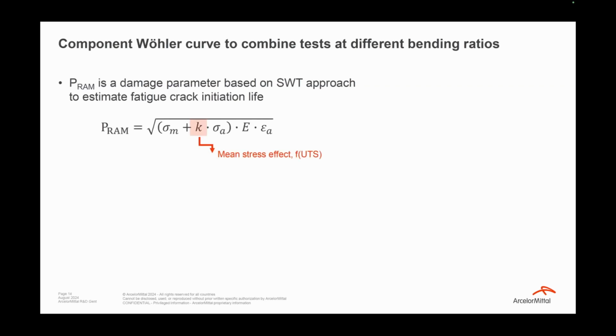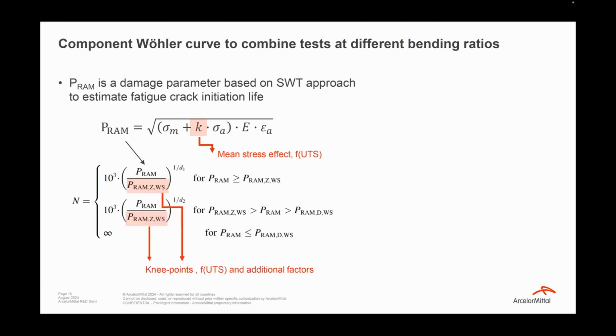There is a certain damage parameter which is called PRAM. This is based on Smith-Watson-Topper approach. This is simply a multiplication of your stress amplitude and strain amplitude with the Young's modulus, and then you take a square root. So you take into account both of them. And there is a certain K parameter which takes the mean stress effects. I mean, there are more equations, but due to time constraints, it's not very smart to really go in detail to put some numbers.